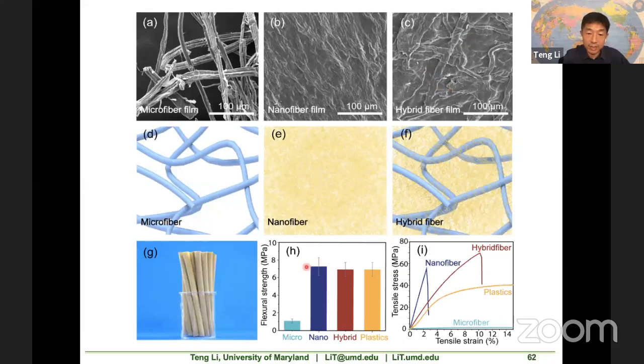And we did the flexural test. You can see that the pure microfiber straw, which is a typical paper straw, has a much lower fracture strength. However, the hybrid one and the pure nanocellulose one are comparable to commercial plastic straws. And in terms of tensile strength, the hybrid one is also stronger than the typical plastic one, although it's not as ductile as the plastic one. But in terms of the function of the straw, the mechanical performance is more than enough.